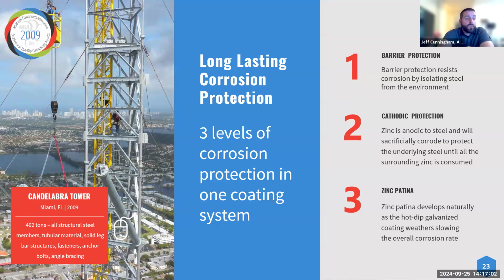All right, so first and foremost, it is that long-lasting corrosion protection. You actually get 3 levels of corrosion protection in one coating system. First is going to be a barrier protection, because the barrier protection resists corrosion by just isolating that steel from the environment. It's a full immersion process, so every piece of that steel is coated by zinc, therefore isolating that steel from the environment. The second level is going to be cathodic protection.